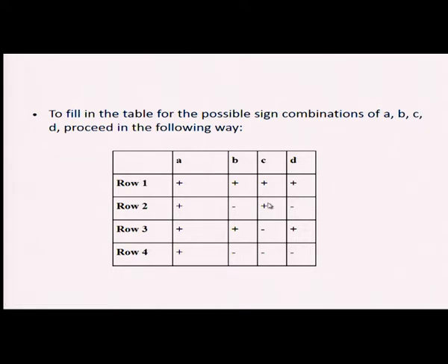If you take this as A, B, C, D, we have another set, this is another set. That is what we are telling: direct methods are multi-solution in nature. For every set we can have a combined figure of merit, and whichever has the largest value as per the SHELX program, that is the best set. So, this is called hand propagation.